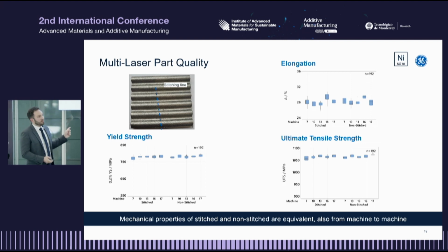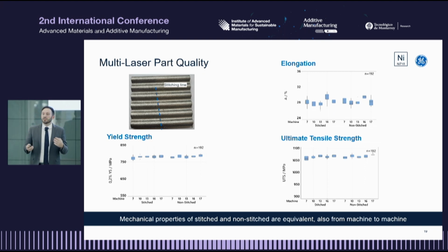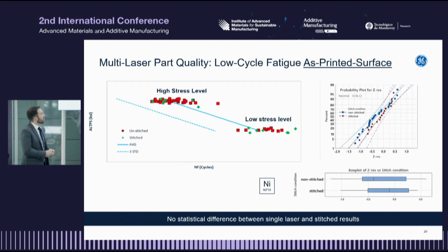But what I just showed you on the prior slide seems to be a surface issue and not a bulk issue, and I don't see a gauge section in here. So the next logical step is to say, I've machined away the area that I most care about, which is what's happening on the surface. Surfaces tend to be the location for initiation of failure in fatigue applications. So to fix that, we went through and tested coupons with as-printed surfaces on them.